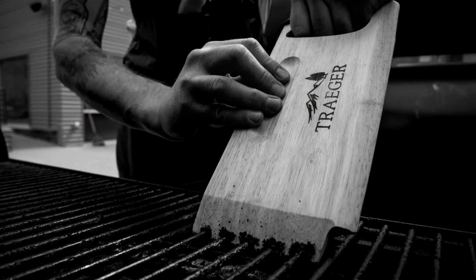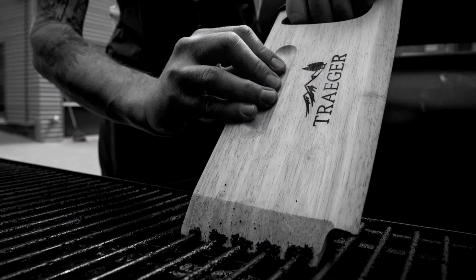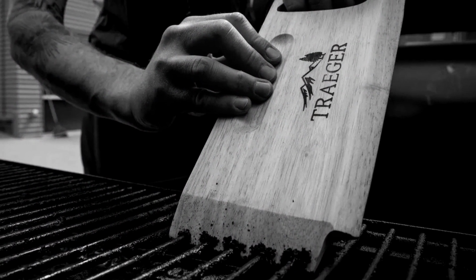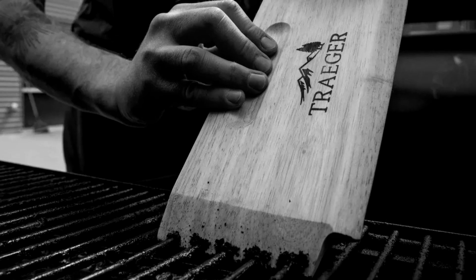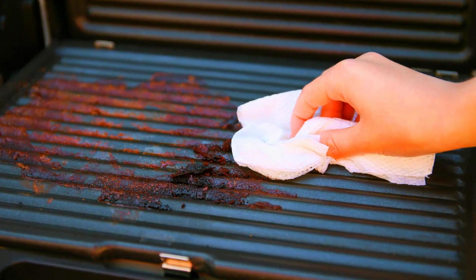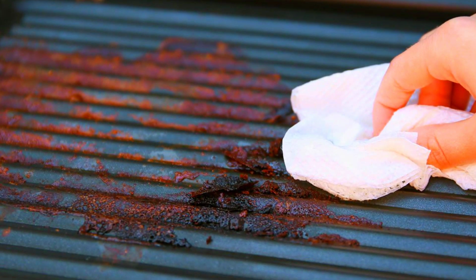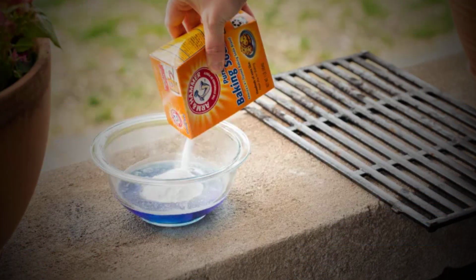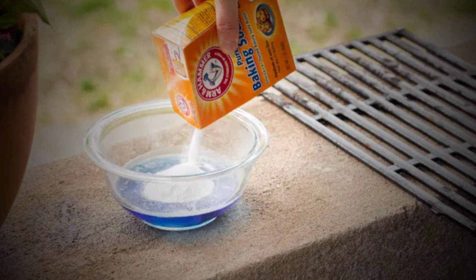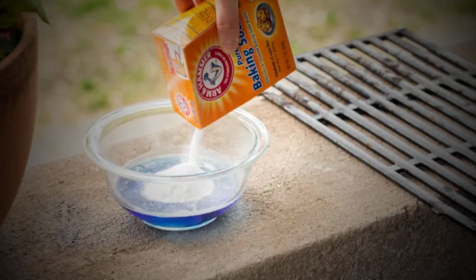not reach. Work an alkaline ash or baking soda paste over anything still dark with a palm fiber brush, then dry it immediately. Burn off for 5 minutes and wipe on a teaspoon of neutral oil at the end of every single cook. And clean it hot at the end, never cold at the beginning.